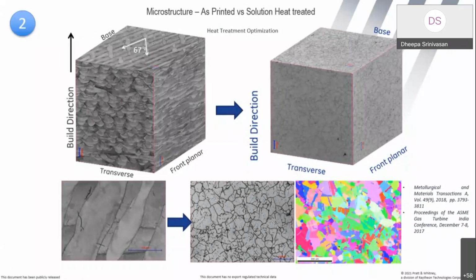And here, as I said, one of the biggest challenges, yes, we were able to do a whole bunch of heat treatment optimization. Again, this is another master student's thesis, in order to get a nice recrystallized microstructure, such as what you see on the right. And here we kill two birds with one stone, namely the heat treatment that is necessary for the microstructural evolution of the additive cobalt chrome moly versus the actual microstructure that is going to correspond to the best mechanical properties.